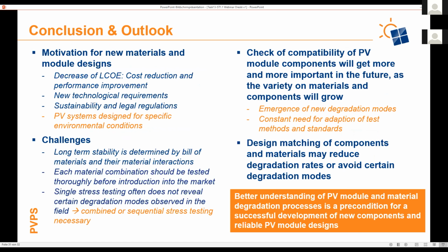The challenge is always the same. The long-term stability of a PV module is determined by the bill of materials and their interactions. And therefore, each material combination must be tested thoroughly before being introduced into the market in order to avoid such unexpected failure modes. And also, as I showed, single stress testing, as is done very often in industry still, often does not reveal certain degradation modes which are observed in the field.